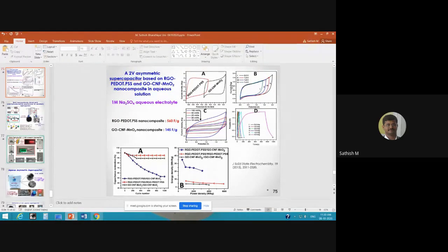Sometimes initially the system will be stable, but after some time you could see there is a stability issue. Even here we have observed some issues like this. You could see the charging takes a very long time, but the discharging is very short. That means there is some kind of evolution which takes place at a very minor level, so you could see a small current. But concept-wise, this could be used, but I will not suggest going for a 2 volt device using this combination. Thank you, sir.